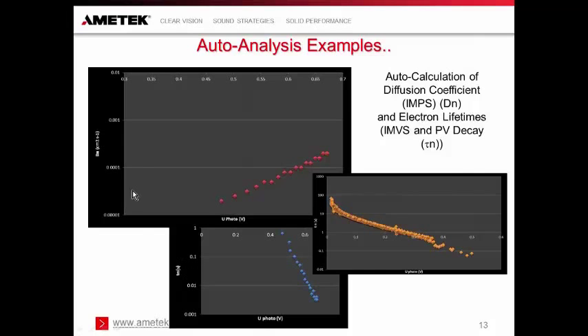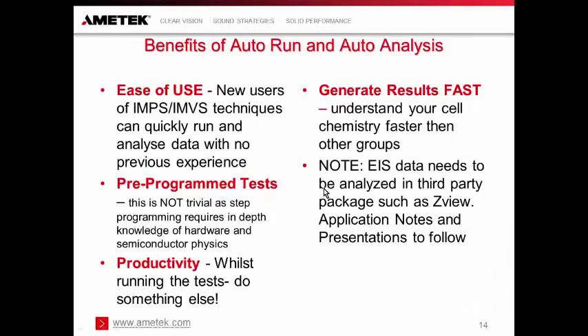As I said at the beginning of the presentation, what we want to do is optimize diffusion coefficient. In other words, make it as fast as possible. We want the electron lifetime to be as long as possible for better cell efficiency. So one could, in theory, overlay many plots of diffusion coefficient for different cell chemistries and electron lifetime for different cell chemistries and compare and get a much better understanding of how the chemistry is affecting the efficiency of the cell. So clearly the benefits of auto-run and auto-analysis are as follows.